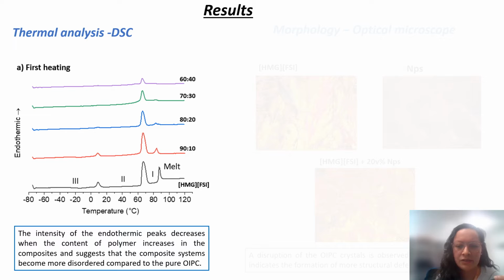The thermal analysis of the composites after adding 10, 20, 30, and 40 volume% shows that the intensity of the endothermic peaks of the organic ionic plastic crystals decreases with the addition of polymer. It means that we are creating a more disordered environment around this material.